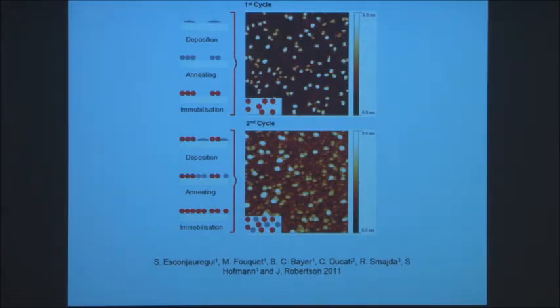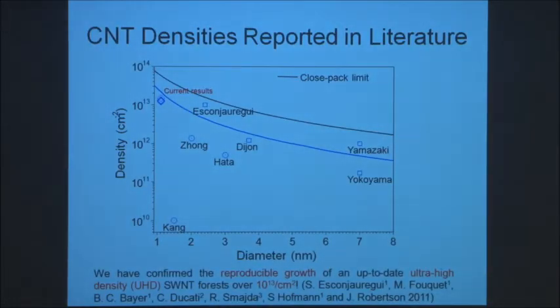And so what our clever students did is they immobilized these ones by oxidizing them. Then you put down more catalyst. They don't then agglomerate. And then you reduce them. And so by doing that a few times, we've actually managed to get up to the situation where we can now get 10^13 per centimeter squared, which is exactly what you need for the packing density in these holes. So we're getting close to the densities we require.